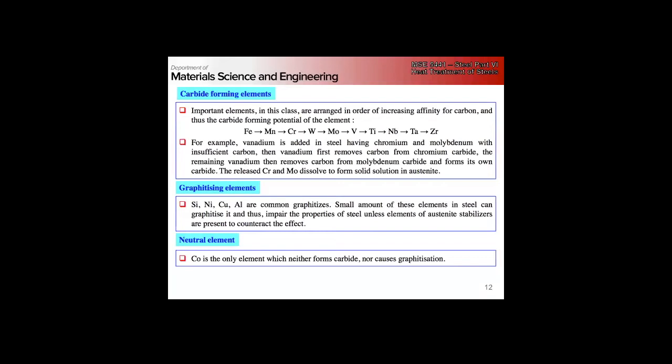Or there's no ranking by dissolution temperature, right? So if you are in the melt and you cool quickly, it could be that, yes, the titanium carbides are more energetically favorable, but they're slower to form, right? So this is ranked basically just by enthalpy of formation, right?